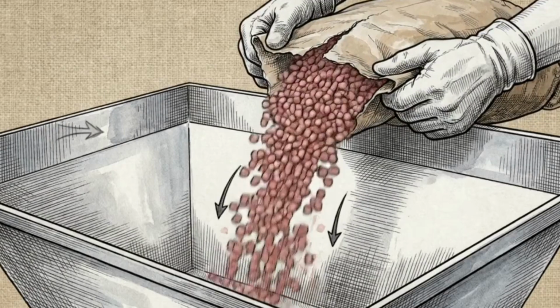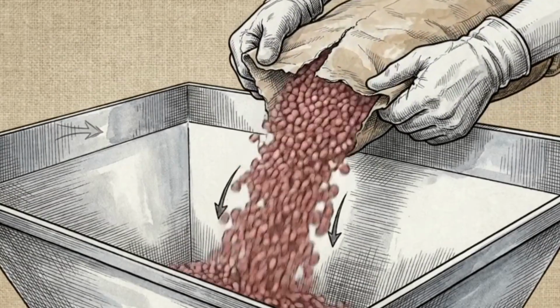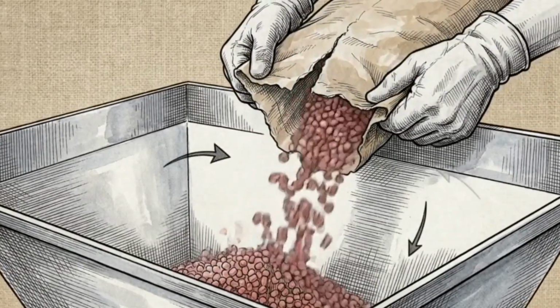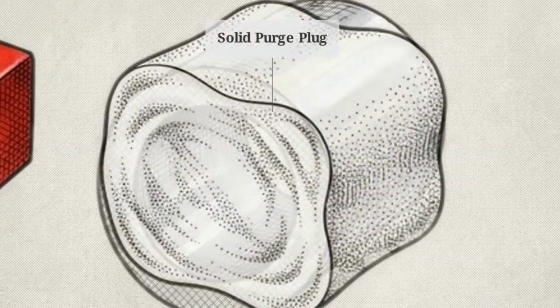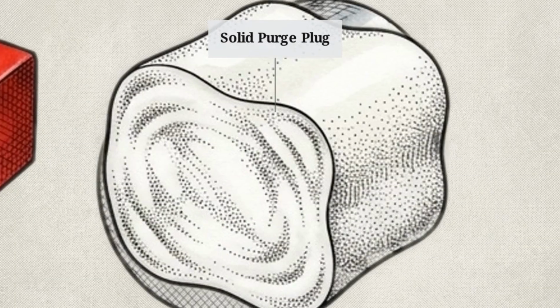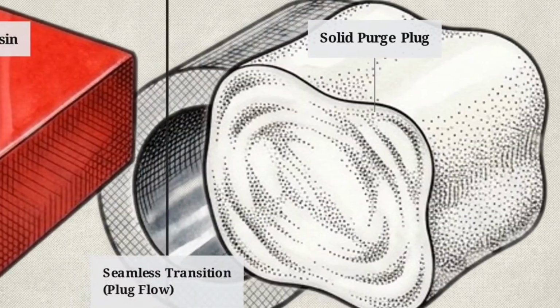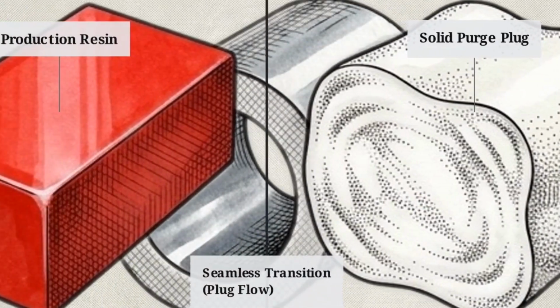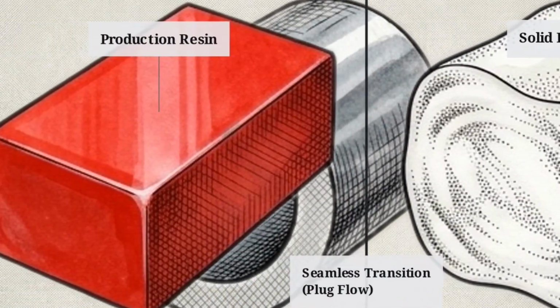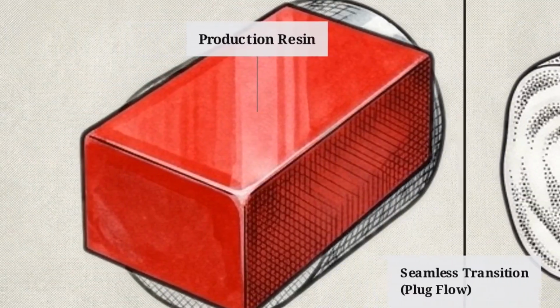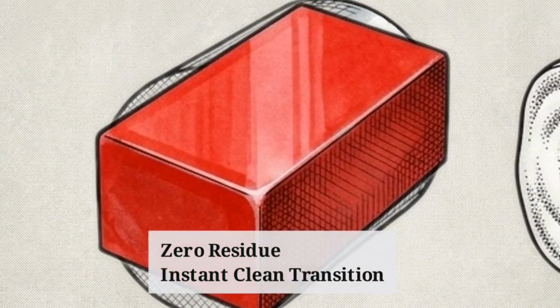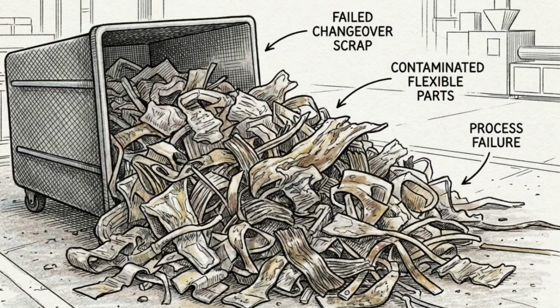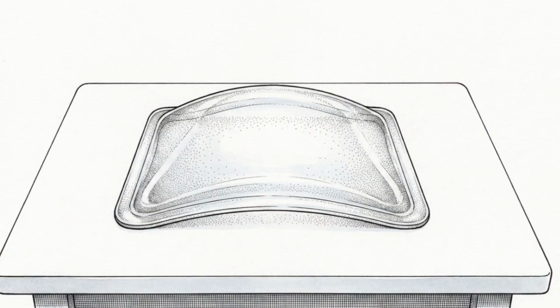Step 3. The moment your purge output runs clean, load your next production material into the hopper immediately. Because this method uses no carrier resin, there is no leftover liquid film inside the machine to dilute the incoming run. The incoming production material easily and completely displaces the solid, thermoplastic purge plug. Warning: if you find yourself running massive volumes of new material just to achieve a clear part, the initial purge was not executed correctly. An immediate, clean transition proves the barrel is decontaminated and ready for production.